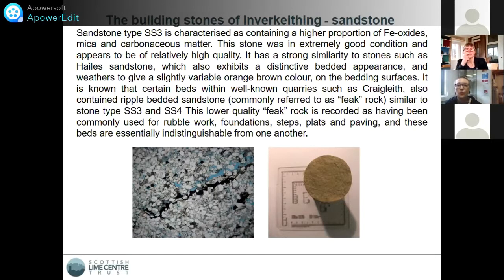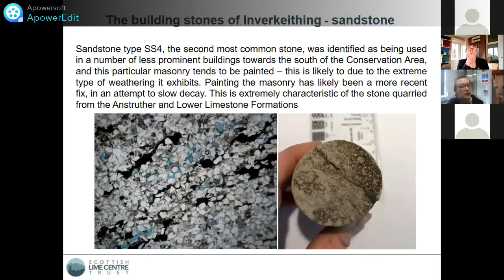and it quite often gets called a feak rock, and this is just because it has these really fine laminations of iron oxide and carbonaceous matter, which are these opaque minerals. And you can see there is alignment there, and it's not as obvious in the hand specimen, but when you look at it at the microscopic scale, you can really see that there. And because of the type of stone, it tended to be reserved for use in foundations and rubble works and pavings and things. And it is very similar to this one, which is Sandstone Type 4 that we found. And this would be the second most common stone that was identified.